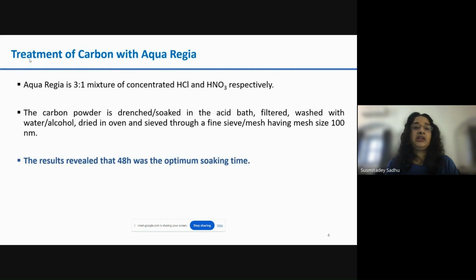So the first method of modification of carbon black is by aqua regia. So aqua regia is used, in which the carbon black is dipped for 48 hours. And after this 48 hours of soaking time, we have taken it out. We have filtered, washed, and dried it in an oven, and then sieved it through a mesh